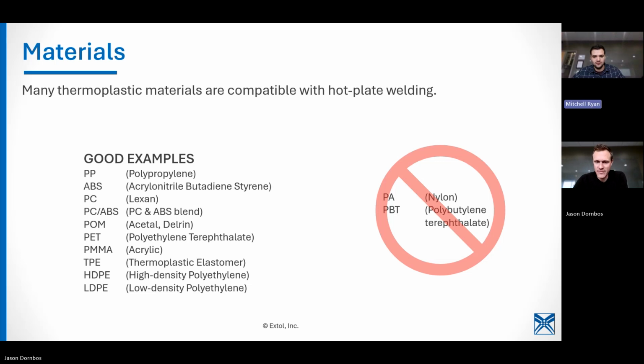There's a couple that you want to steer clear of, and that would be nylon and PBT. They're really sticky, and it's really difficult to get those to not stick. Even with non-stick coatings, it's hard to get them not to stick like crazy to the heated tooling. The challenge too is they require higher temperature, higher than what your Teflon coating will allow. So there's not common coatings on the market to prevent those from sticking. So you typically use non-contact welding methods: vibration, IR, hot plate hover for those sort of technologies.